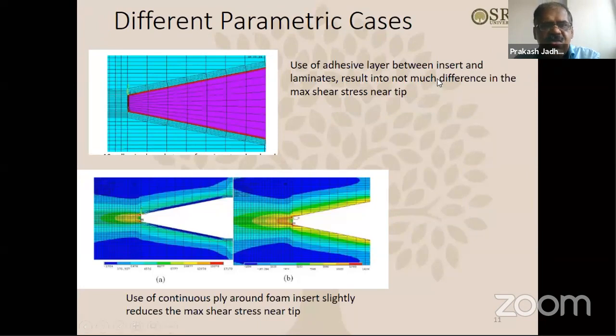Then again, there were some more parameters. Like if you use an adhesive layer between the inserts and laminates, like this is the embedded foam insert, and these are the carbon laminates. If you put adhesive there, what is going to happen? The addition of this adhesive did not have much impact on the interlaminar shear stress level at the tip. Also, continuous ply.